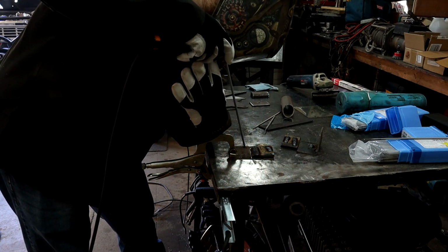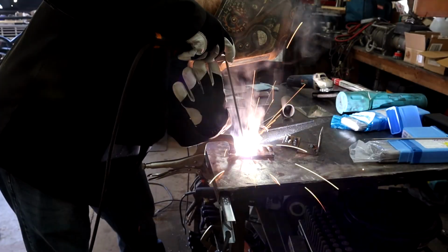All right, so we switched up to the 1/8" 7018. It also ran very well. First pass was about 55 or 50 amps. Second pass about 55. This is the 50-volt pass here, which I did like quite a bit better. Overall, it ran pretty smooth. You can see the puddles flowing out nice. I'm pretty happy with the way this thing runs.